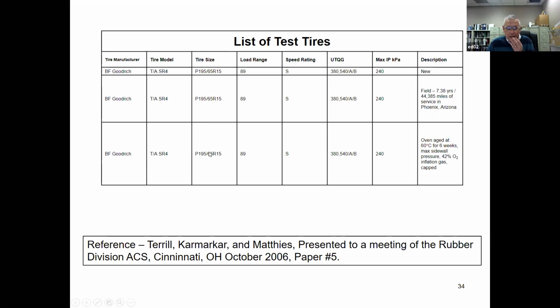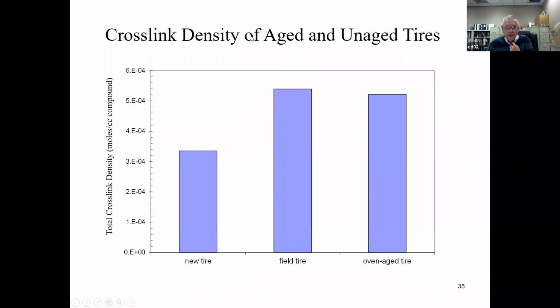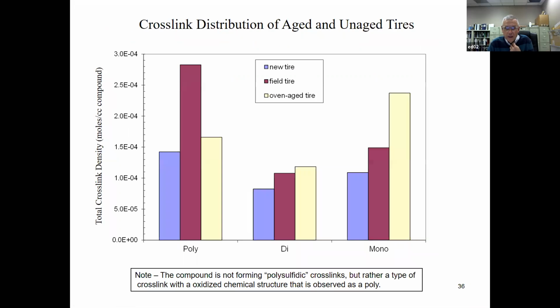Okay, and then just one more slide here. So two more slides here associated with the background. So these are the tires: the new tire, the field tire, the oven age tire, which we described earlier. And here's the crosslink density results that we talked about earlier: the new tire, field tire, oven age tire. And then here's the crosslink distribution of those three tires, with the formed crosslinks showing up as polysulfidic for the field tire, and the new crosslinks formed during oxidation in the oven age tire showing up primarily as monosulfidic types. We say the compound is not forming polysulfidic crosslinks, but rather a type of crosslink with an oxidized chemical structure that is observed as a poly.